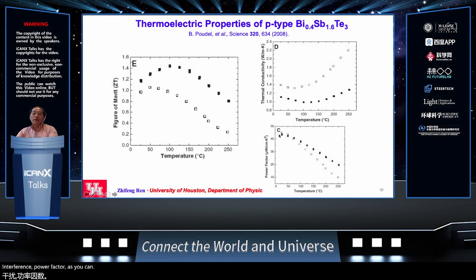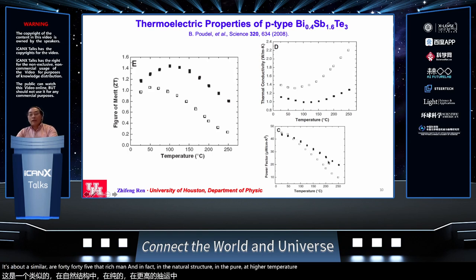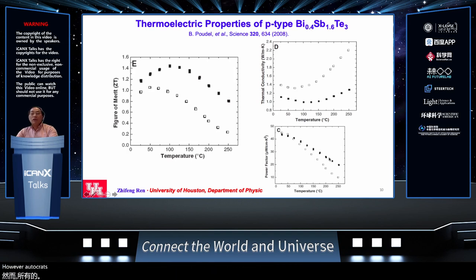As you can see here, the power factor at room temperature, both bulk and nano, is about similar, around 45 in that range. And in fact, the nanostructure material at higher temperature has an even higher power factor, which is very good for low temperature waste heat recovery for electrical power generation.